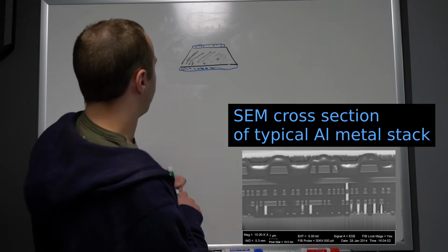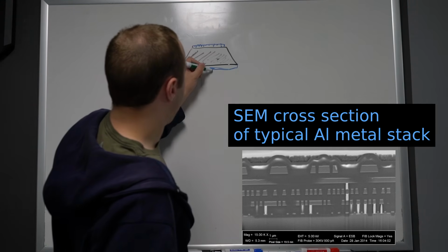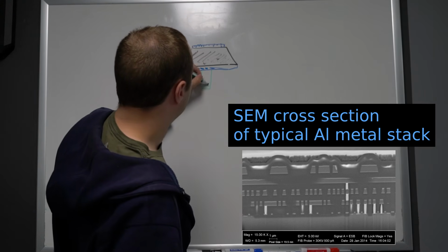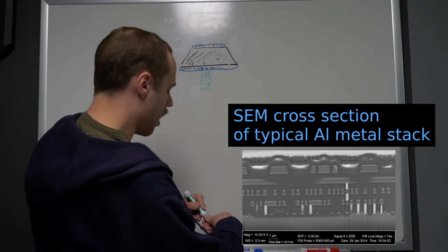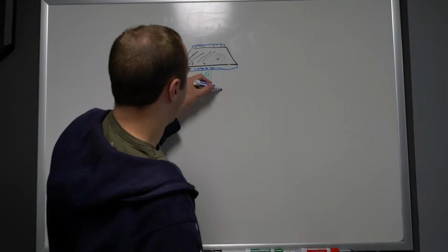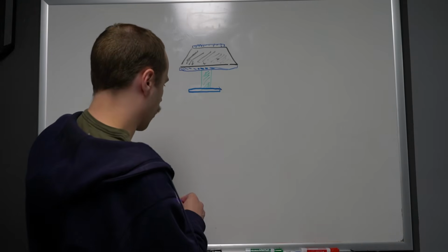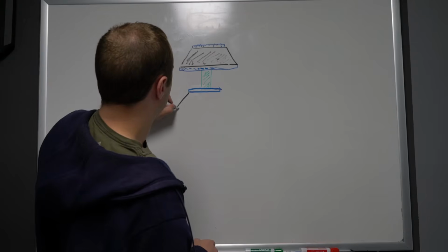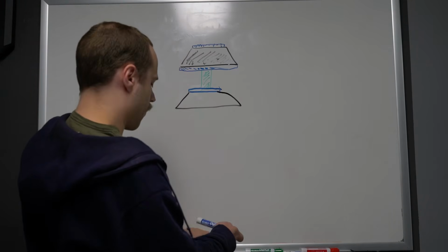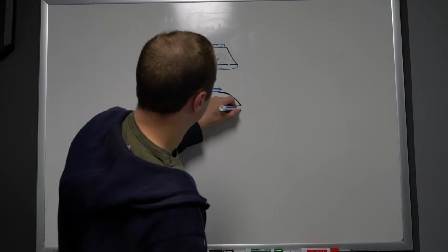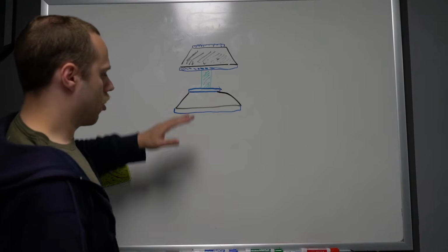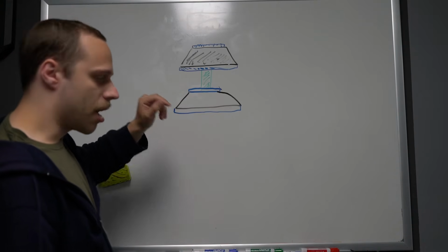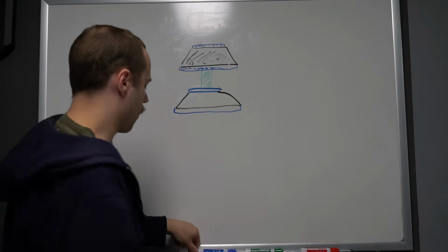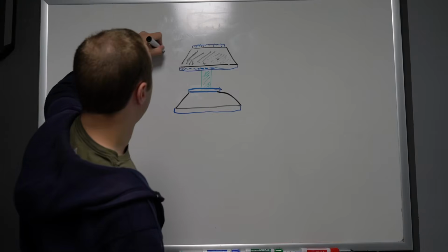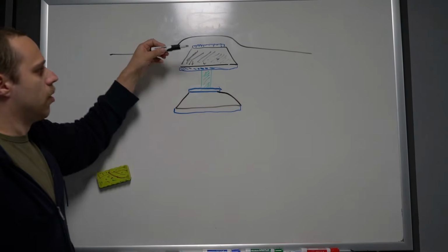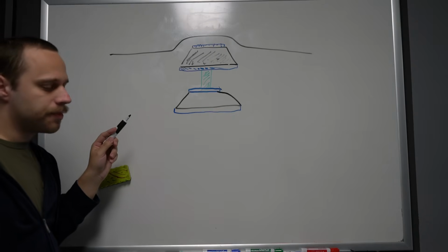And then as we go down from this layer to the next layer down, we're going to have the vias, which on devices of this generation are typically tungsten. And then going down from there, we've got the cap layer on the next metal layer down, and then our aluminum conductor, and then our adhesion layer below that. And so we have a total of 3 conductor layers and then the polysilicon below there. So our goal is starting from this top surface, which as I mentioned is a little bit rough, we want to go down 1 layer at a time as precisely as possible.